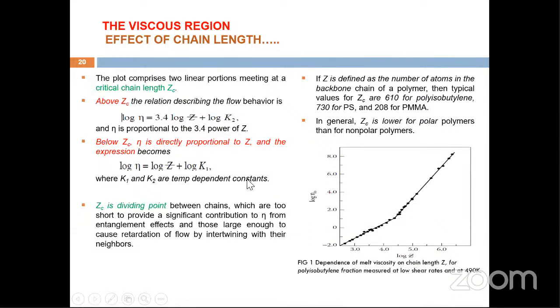This is Z critical, ZC. Above this ZC, the flow behavior of the viscoelastic polymer is explained by the expression log eta equals 3.4 log Z. Here the slope is 3.4, where the chain lengths are higher than a particular length. And below this critical chain length, this equation is followed, where the slope is 1. Here the slope is 1, here the slope is 3.4. So this is the dividing point.